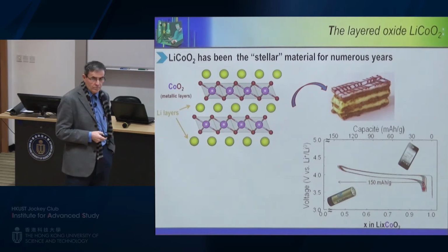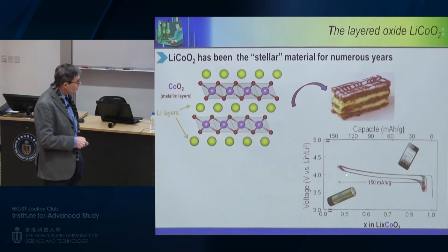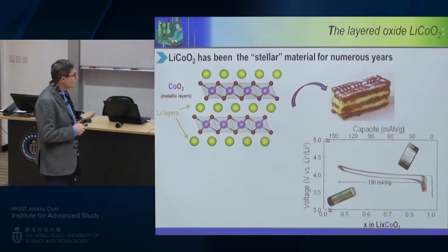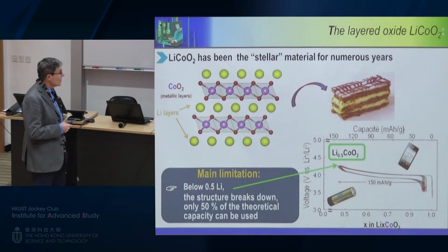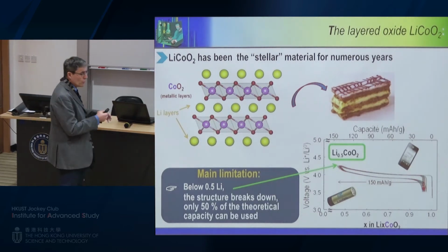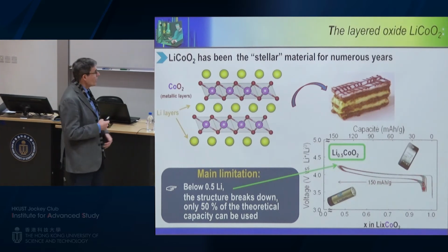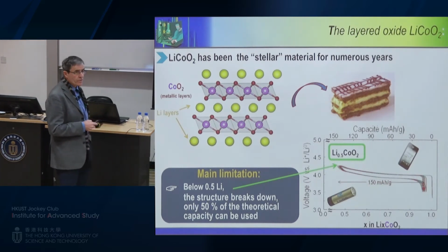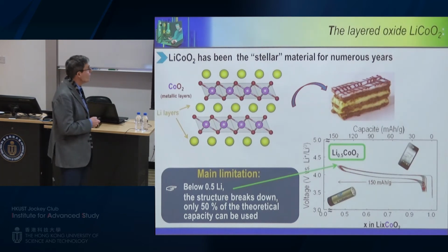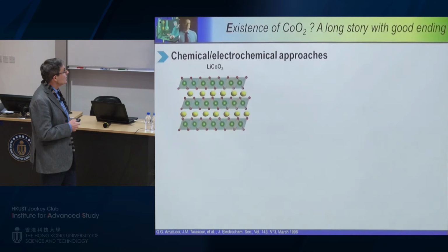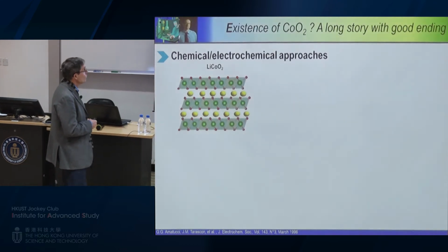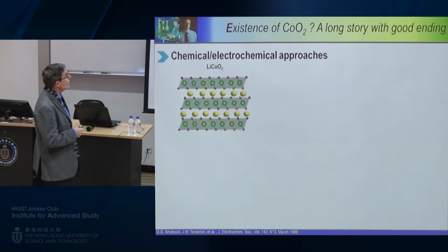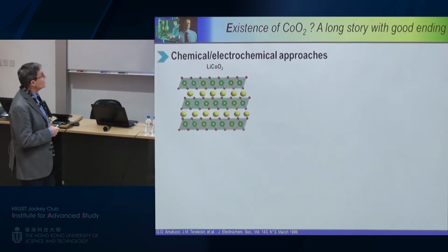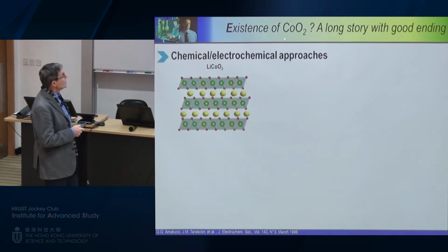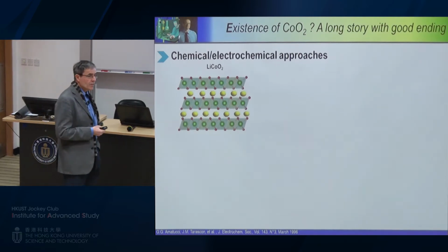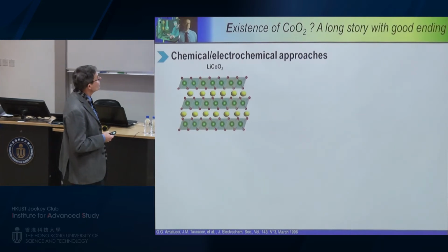150 milliampere hours per gram. But unfortunately, you can see, we cannot remove more than 0.5 lithium. And the main limitation comes from the fact that if you try to remove more, the structure breaks down and the layers fall apart. So through the years, chemists have really tried to improve this via chemistry. And in order to understand these materials, what happened is really to look at what the reaction mechanism is. And the question you are asking is, can we remove more than 0.5 lithium per cobalt metal?